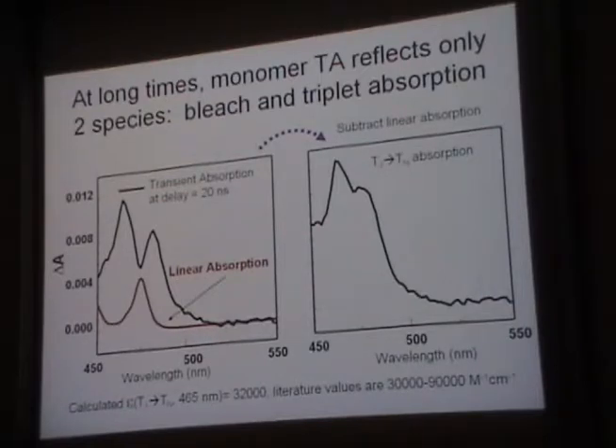So we said, okay, it looks like a mess. What happens if we wait? Tetracene does go to the triplet state. It intersystem crosses with reasonable efficiency, 60%. We should have no more singlet state. Okay, so things should get much cleaner, and they do. And what's more, at long delays, after 20 nanoseconds, it's all in the triplet state. We see a big fat absorption here with a dip in the middle. That dip is the bleach, but it's dominated by this big absorption. That absorption is T1 to Tn excited triplet absorption. Okay, so we do see that in the monomer, just as we expect to.